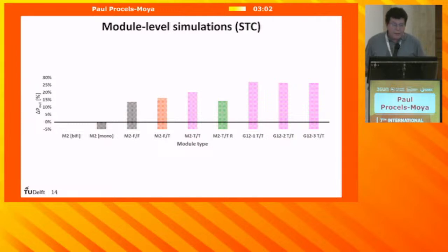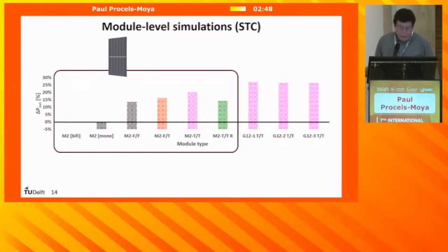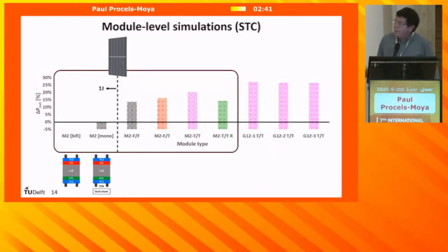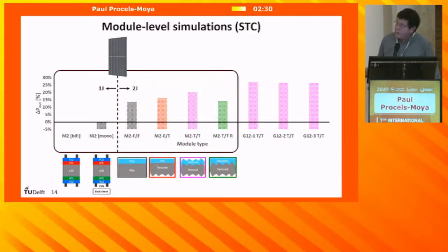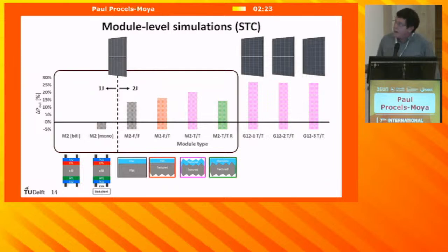Here are the first results from the module level. I'm showing the power output as a function of the module type, so for different modules, different solar cell structures. Here in the black box, you can see that all the results are related to the M2 configuration module. And here I use a dashed line to separate the single junction on the left-hand side and dual junction on the right-hand side for the different interfaces in the tandem system. Additionally, we consider G12.1, G12.2, and G12.3 just as comparison. Of course, the area is bigger, so it's also in favor of these bigger modules.